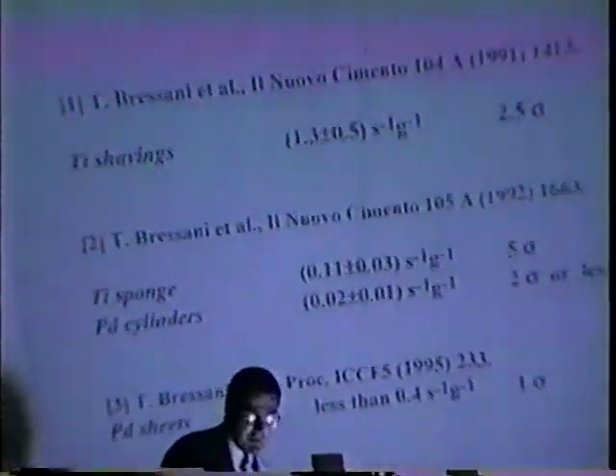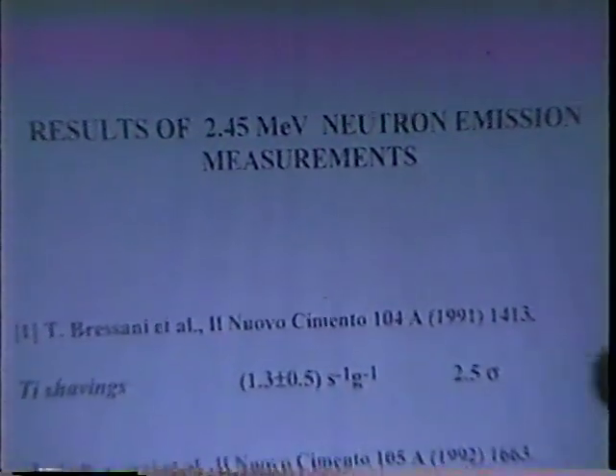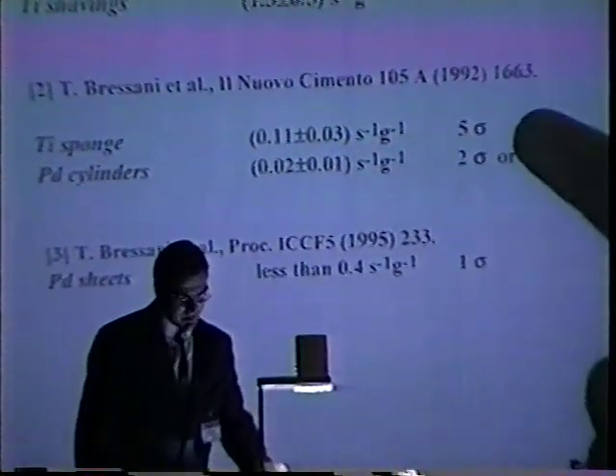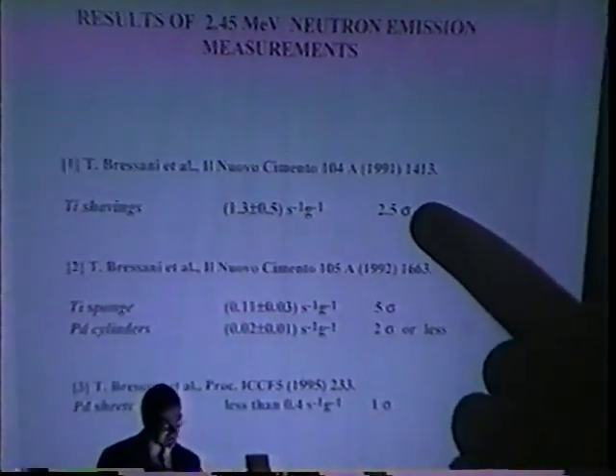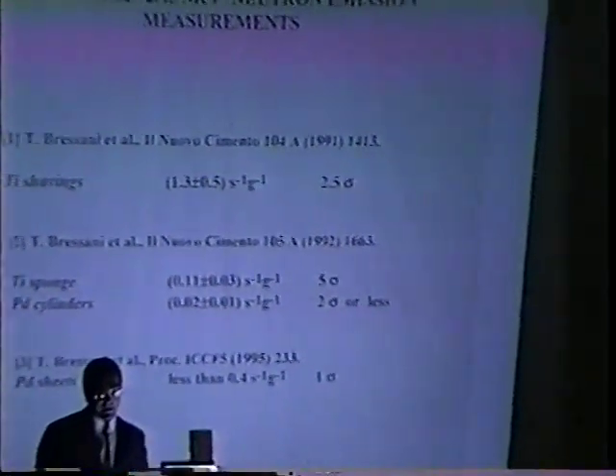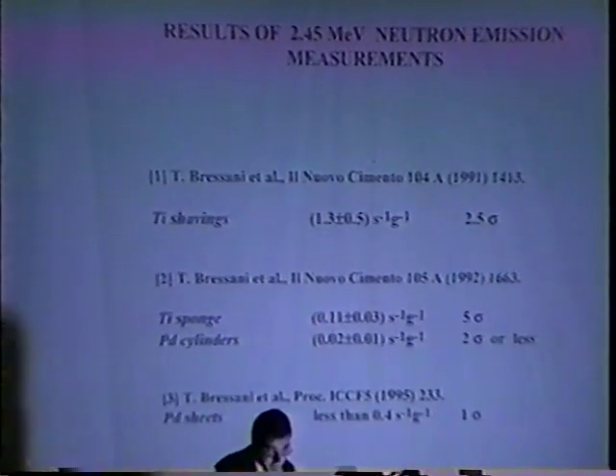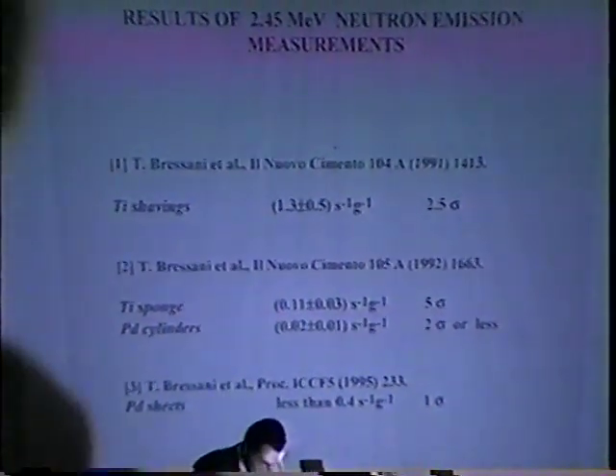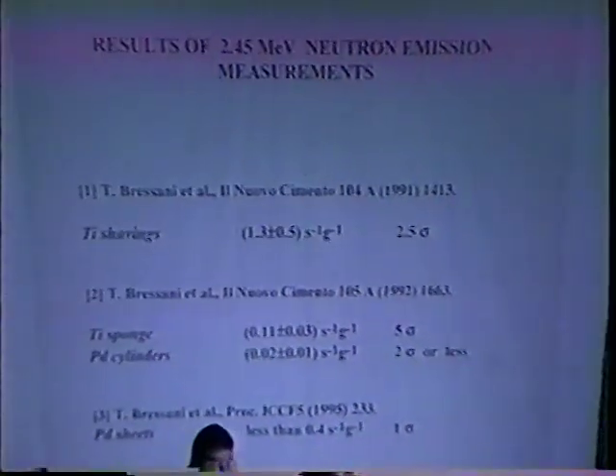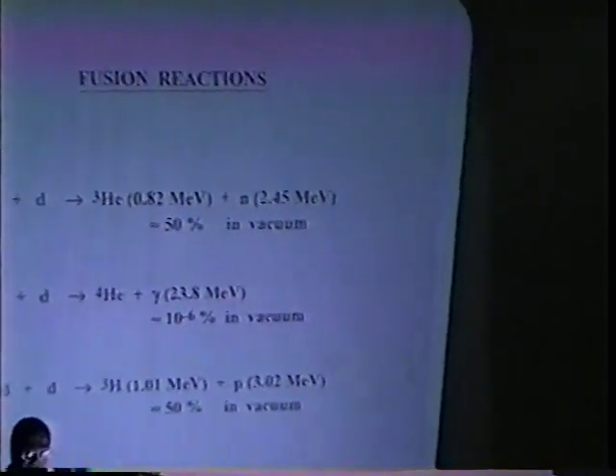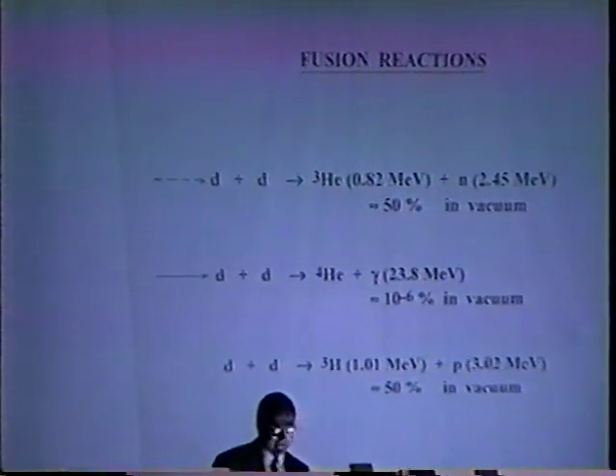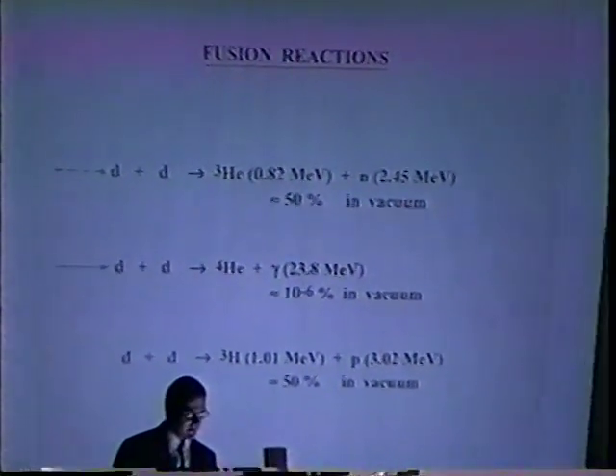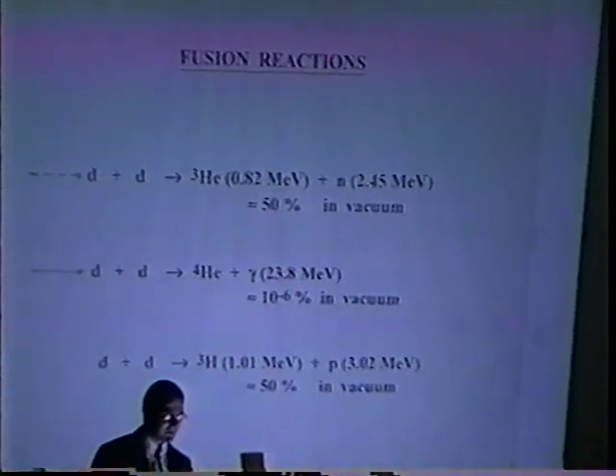What I said before is that the neutron emissions were too low when compared with the excess heat reported by other experiments. We performed several experiments on titanium shavings and on titanium sponge and on palladium cylinders. Sometimes we had flux with a very good significance, but these numbers were too low to be consistent with excess heat reported by that experiment. So that is mainly the reason why we decided to go to the second reaction involving the helium-4 production. I never talked about helium-3 production, and we actually can't perform such a measurement. I mean, a gas analysis in order to find helium-3 is not possible without instrumentation.